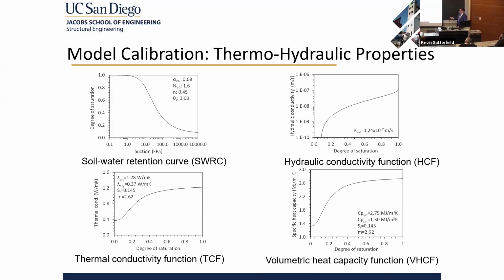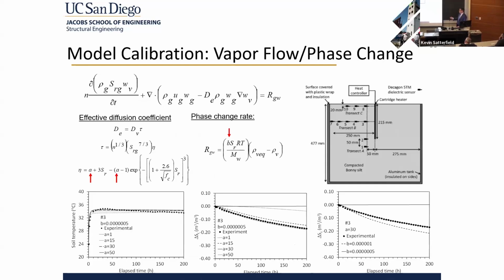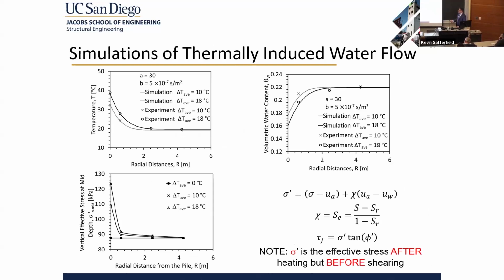We needed to calibrate that using some different parameters for unsaturated soils. And we also needed to calibrate the phase change rate and the effective diffusion coefficient using some tank tests. So we did all these in support of trying to simulate what happened in the centrifuge test. But with that, we could simulate the temperature distribution and the volumetric water content distribution. These are our measurements from the test, and we had a pretty good match with those.